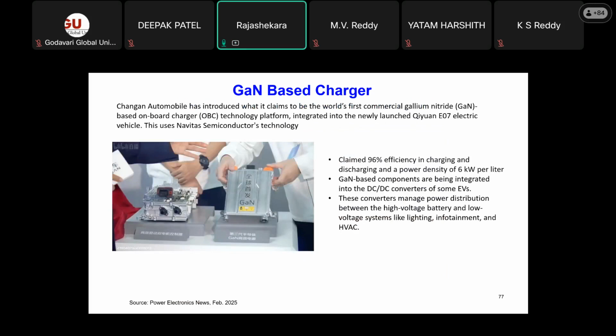This is the gallium nitride based charger. Changan Automobile, near Chongqing in China, also makes a lot of electric vehicles. There are so many electric vehicle manufacturers in China, maybe at least about 50. They demonstrated the first gallium nitride based onboard chargers. They claim 96% efficiency. That is the DC-DC converter for accessory units, for bringing down to 14 volts from the high voltage battery. They also demonstrated a gallium nitride charger. This is with silicon and this is with gallium nitride.